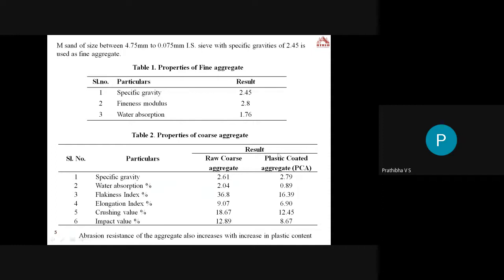These are a few physical properties of the materials used. First, the properties of fine aggregate. We have used M sand, with a size ranging from 4.75 mm to 75 microns. The specific gravity is 2.45, fineness modulus is 2.8, and water absorption is 1.76.